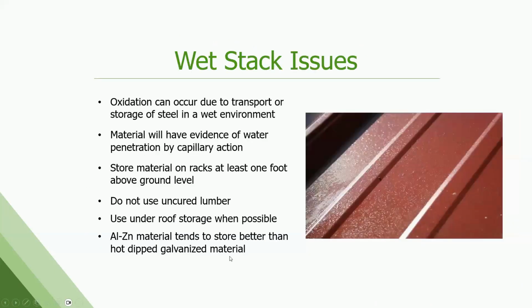Wet stack. This is corrosion that occurs when the panels are stacked together. It can happen in coil form too. So if moisture gets in there and there's not a lot of airflow, that moisture works its way down to the interface between the paint and the substrate and causes corrosion to occur kind of from the inside out and pushes the paint up. Often looks like these little fine blisters or bubbles on the paint system. There's a lot of, again, technical bulletins out there on how best to store product so that this does not happen.